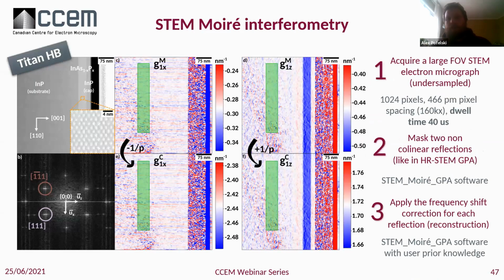So if you summarize this process, again, same sample as before, the indium arsenic phosphide case that has been acquired in large field of view. The part that is important to do is just to acquire the electron micrograph. Experimentally, it's very easy because you are exactly in the same condition as in STEM imaging. The only thing that you have to do is to use a large pixel spacing, so low magnification, and a slightly higher dwell time. That's usually to give a good contrast between the Moire fringes.